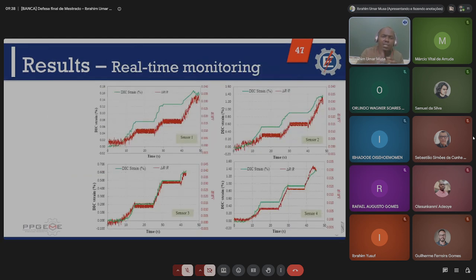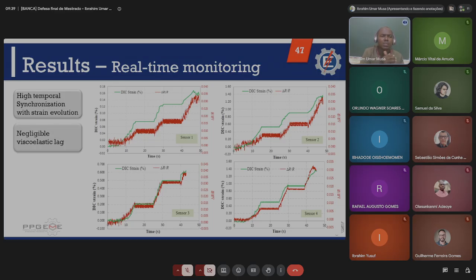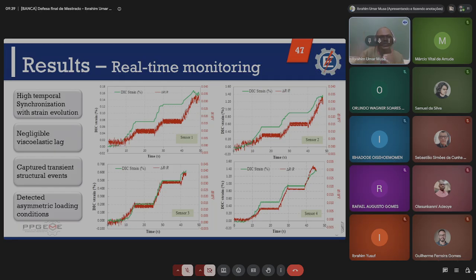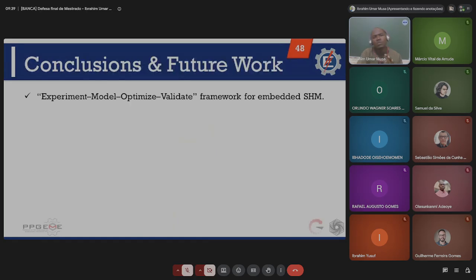And we have the real-time monitoring as presented here, and the same issue was observed zooming in on the magnitude of the amplitude for sensors 3 and 4. And from this real-time monitoring, we were able to see a high temporal synchronization with the strain evolution, and negligible viscoelastic lag was also observed during the strain holds, and it was able to capture transient structural events during the load ramps. And finally, and very importantly, it was able to detect that asymmetry that was introduced by the loading conditions.